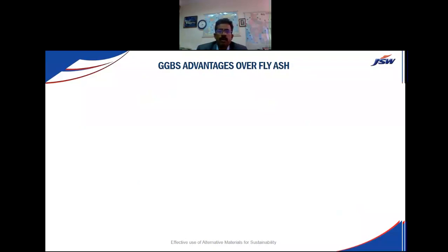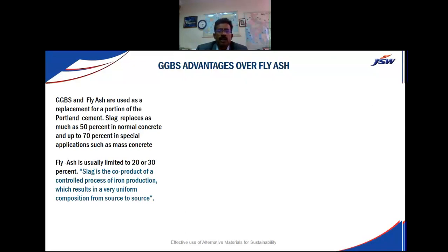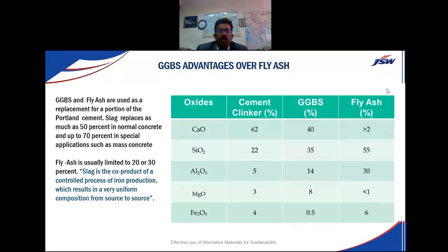I'm going to talk now about how GGBS is better than fly ash. You can see the table here. I can clearly show the calcium oxide content. If you take the pure clinker, it is 62%. GGBS has 40% calcium oxide, whereas fly ash has less than 2%. Silicon dioxide: clinker 22%, GGBS 35%, 55% in fly ash. This is more reactive in the GGBS.